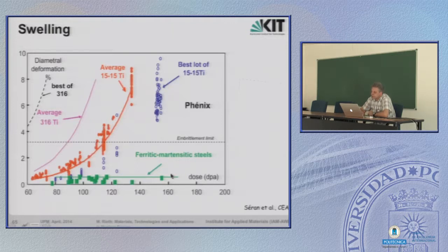But here in green is the swelling behavior of ferritic martensitic steels, or in general ferritic steels. And you see there is a flat line, and this tells us that in BCC structured metals, or at least in ferritic martensitic steels, this is not true for all BCC structures, but for martensitic ferritic steels, the swelling behavior is not at all a problem, since up to really high dpa, very high doses, there is a very low swelling rate. It's below 1%. So this is the big difference.